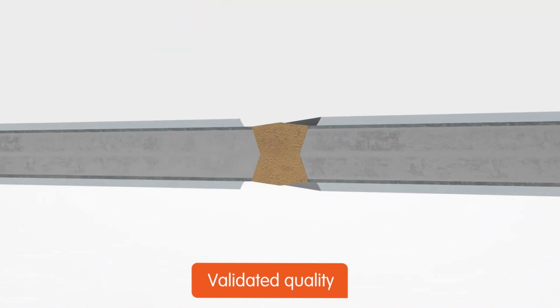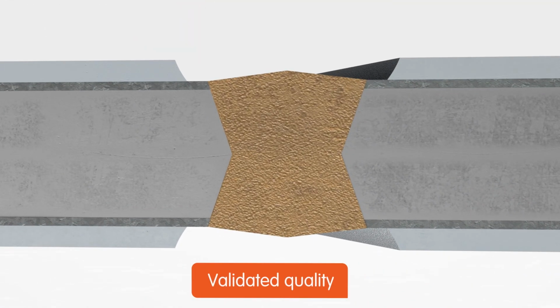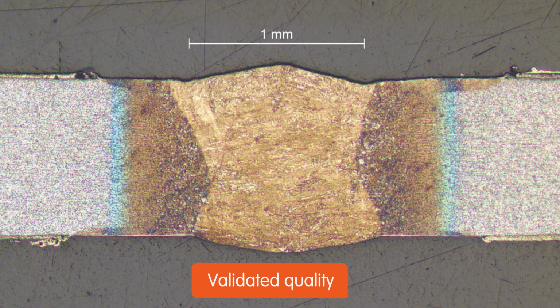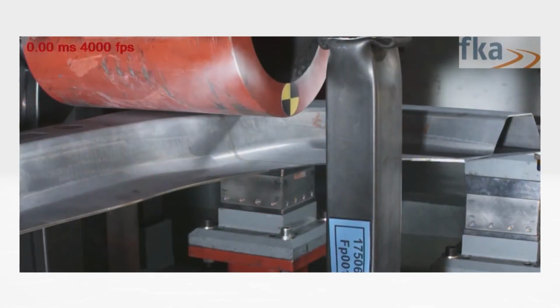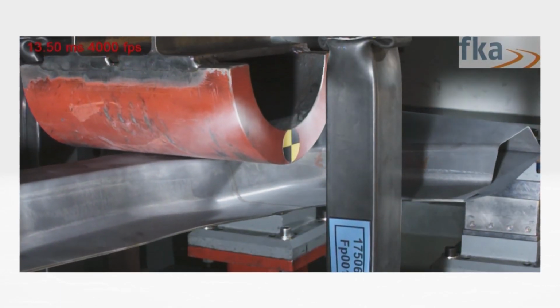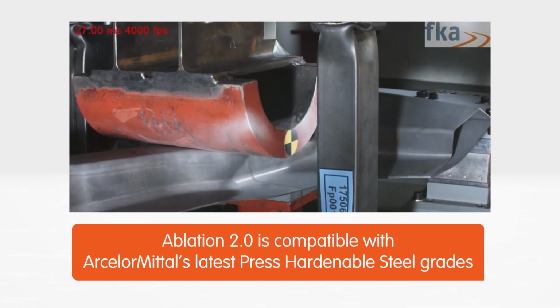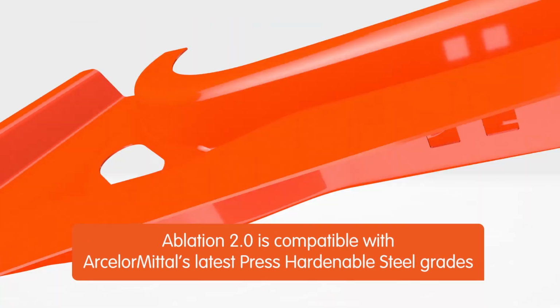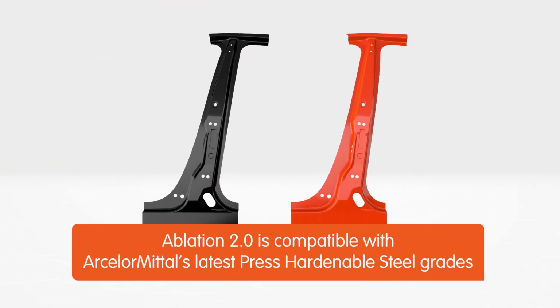The addition of filler wire increases weld thickness, improves quenchability and ductility, extends the process window above 0.3% aluminium, and ensures excellent laser welded blank quality. Laser welded blanks made from Usibor 2000 and Ductibor 1000 and produced using the Ablation 2.0 process have excellent crash performance.